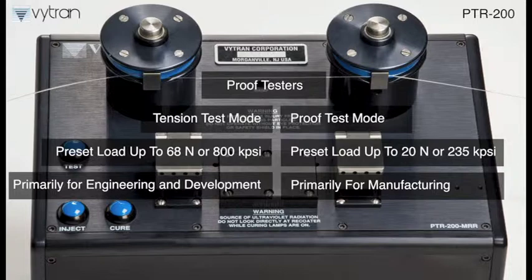The peak tension is recorded and displayed in units of tension such as pounds, kilograms, or newtons, or in units of stress such as KPSI and gigapascals. The long-term reliability of the fiber can be assured by selecting a proof test level approximately three times higher than the applied surface load on the fiber or fusion splice.